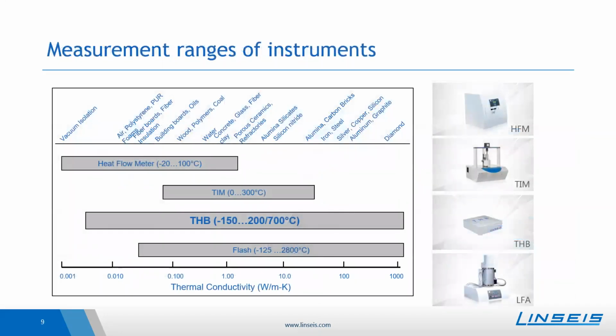Here on this slide, you can see the different thermal conductivity and also temperature range of all of these just mentioned instruments. So one can see that the heat flow meter and the TIM tester focus more on the lower conductive materials up to about 10 to 30 watt per meter Kelvin. And the THB and the laser flash instrument are covering more or less the complete thermal conductivity range. The laser flash has the advantage that it can measure to extremely high temperatures, so also up to 2800 degrees Celsius, whereas the THB is limited to 200 or 700, depending on the type of sensors.